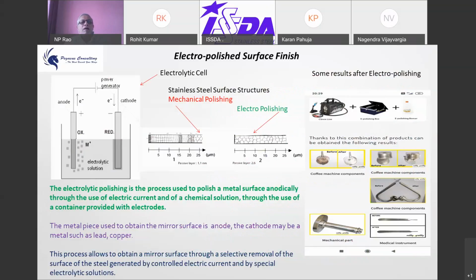Electropolishing. Electropolishing is an electrolytic process. As compared to mechanical polishing, electropolishing can also give you a very smooth, shiny, mirror-like surface. The advantage is that at the surface of the material, the passive layer is not much damaged in electropolishing, whereas in mechanical polishing, it is likely that the surface is slightly eroded. And the structure of the surface remains almost the same in electropolishing.